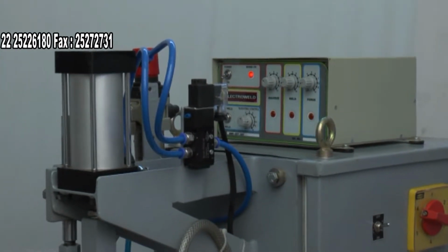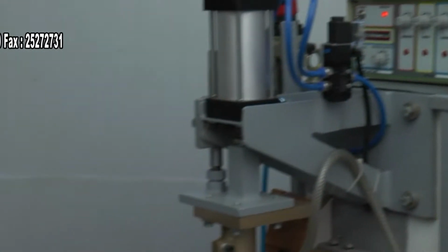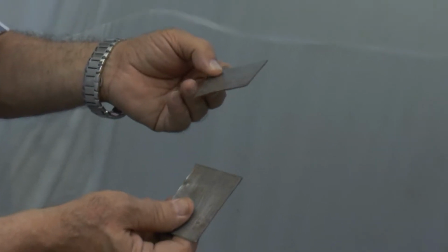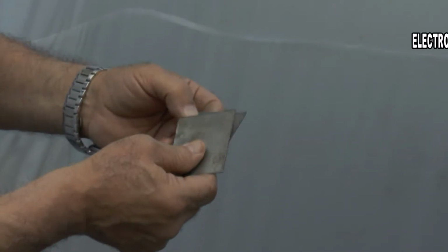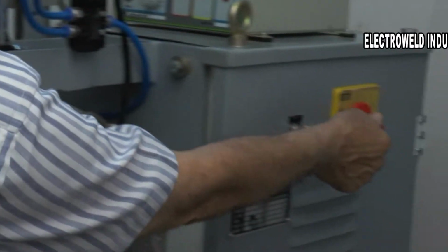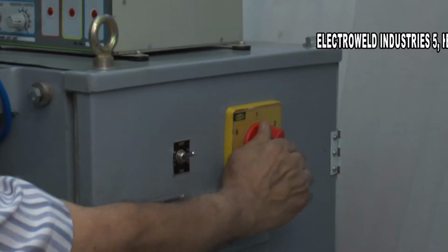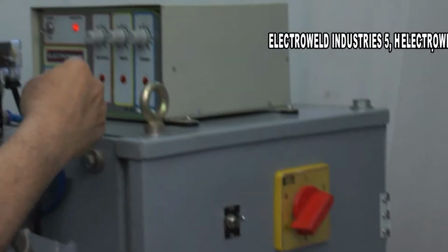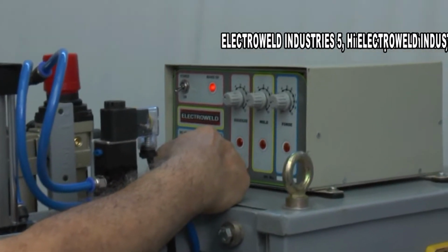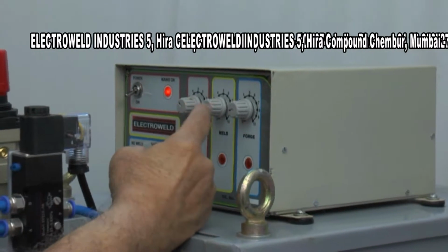We'll once again show the spot welding of 16 gauge, say 1.6 mm plus 1.6 mm thick components. For this again, we have to adjust the current over here. We keep at number 2, and then the fine current, let it be at number 5. That is 50% of the particular tap. Then squeeze time, let it be same. Weld time, let it be same, say about 10 cycles. And the forge time, again 10 cycles.